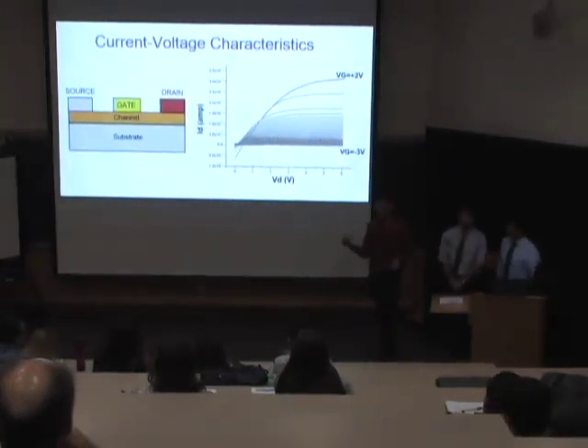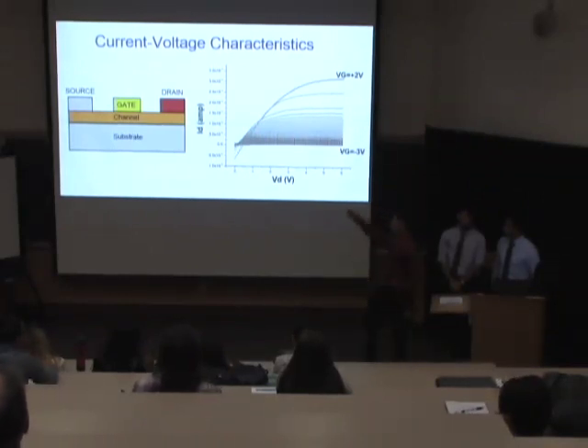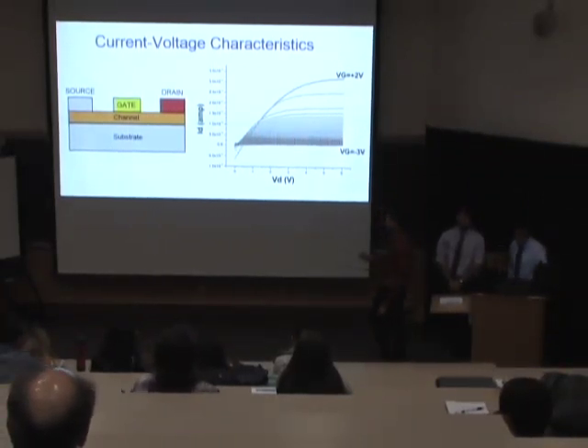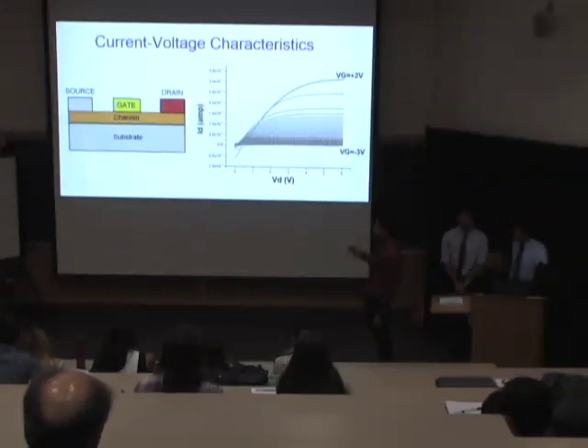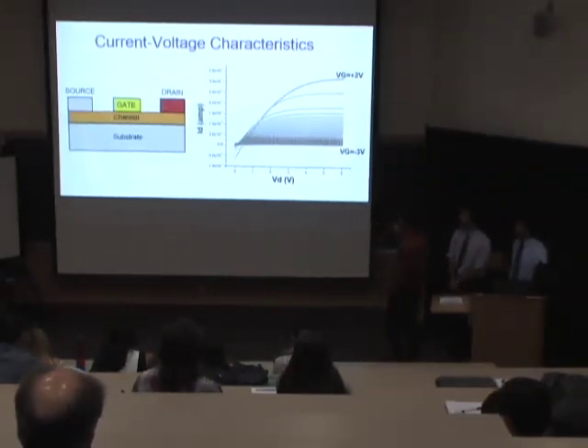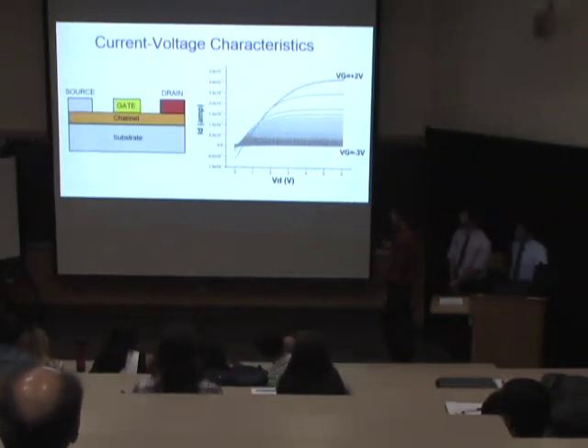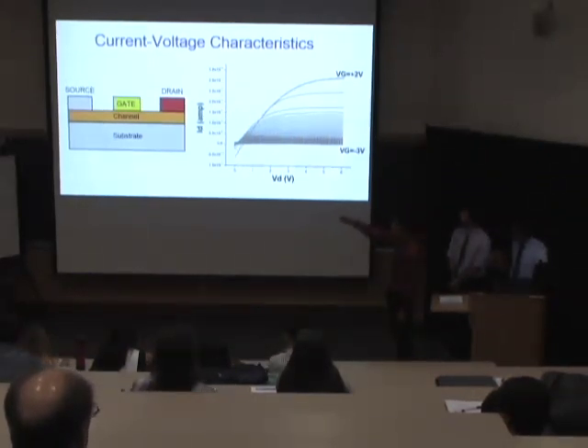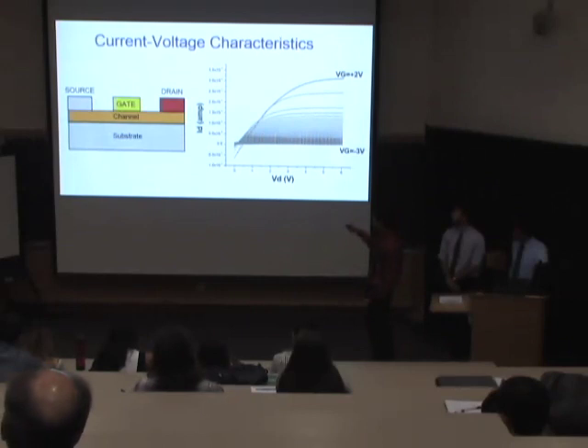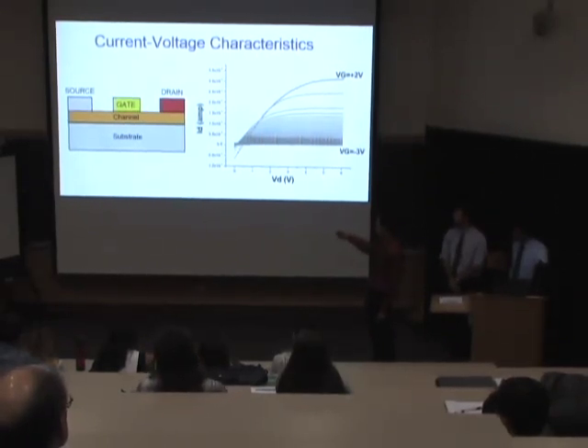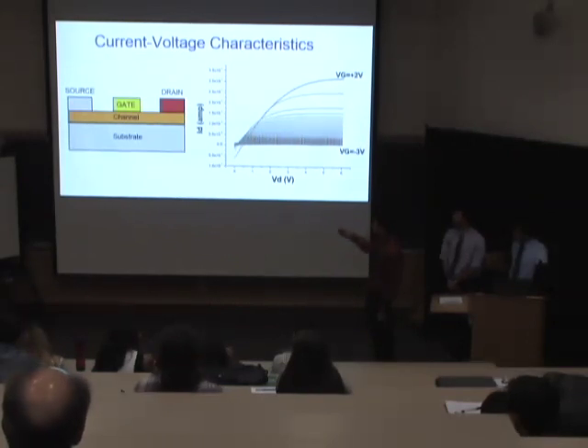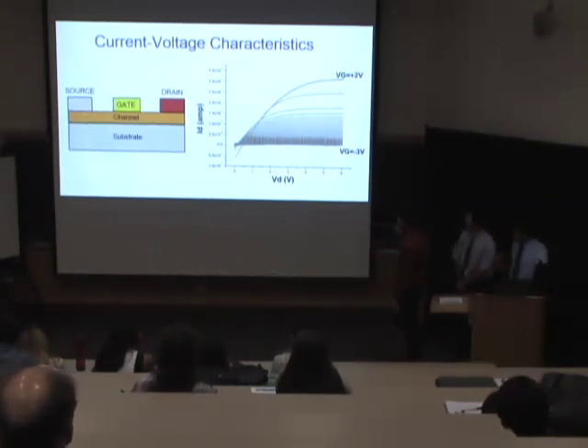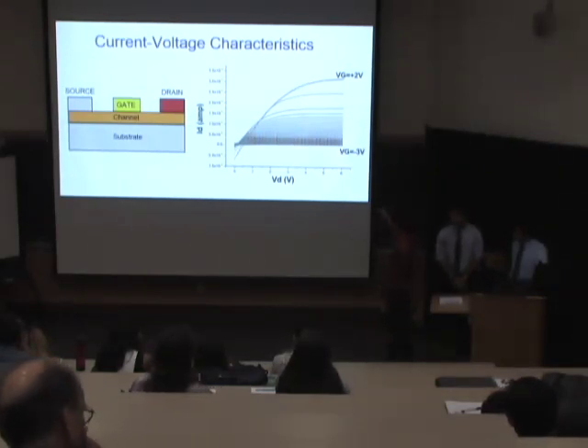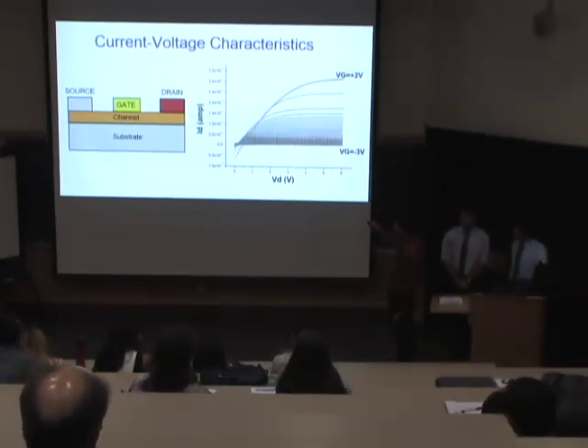When we finish characterizing our material, we want to know what's the current voltage it can hold before it starts leaking. How we do that is we go to the probe station and we put 1 probe on the drain, 1 probe on the source, and 1 probe on the gate. This shows how much voltage we have on the gate. This shows how much voltage we're applying to the drain and source, and this is being swept from 0 to 6. What we're actually measuring is how much current is in the channel. So we apply it at 0.1 intervals to the gate, as you can see. Each one of these lines means 0.1 more.